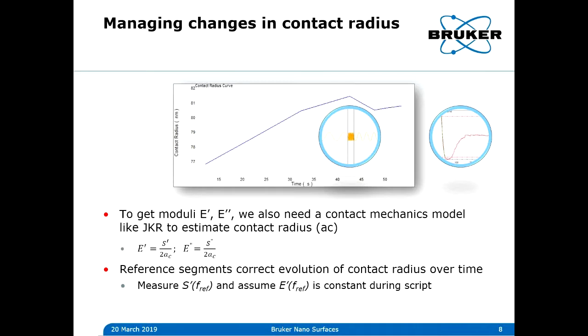And that's why when we did our comparison there, we looked at an interface that had different materials in it, and we looked at where it looked like the modulus was leveling off. So that's the source of our comment about the resolution. If you were to look at, say, a block copolymer or something like that, I've seen significantly higher resolution images than that, but I can't tell you that they're not being influenced by the adjacent components in the material.